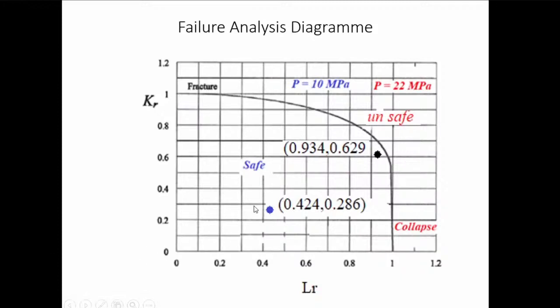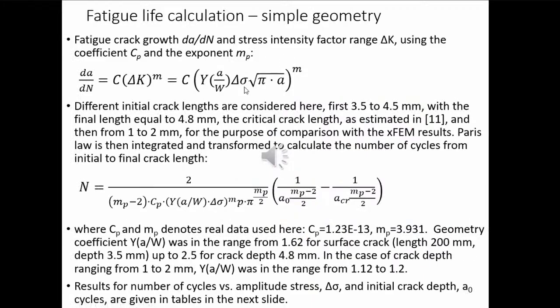Both are inside the safe part of failure assessment diagram, as you can see here, but one with relatively low probability and the other with relatively high probability. And then for the fatigue, we simply use Paris law. With some simplification, we can integrate it directly to get number of cycles, which is not very precise, but it is conservative and, of course, in engineering term, usable.